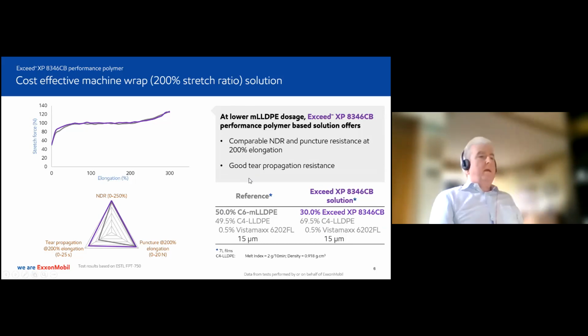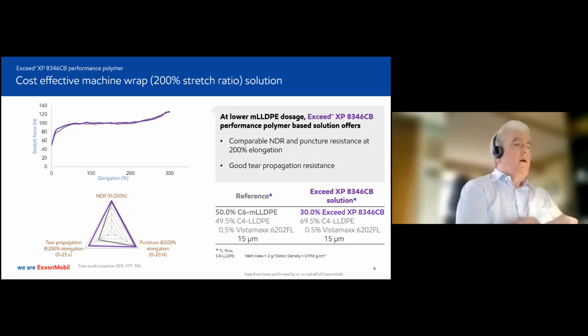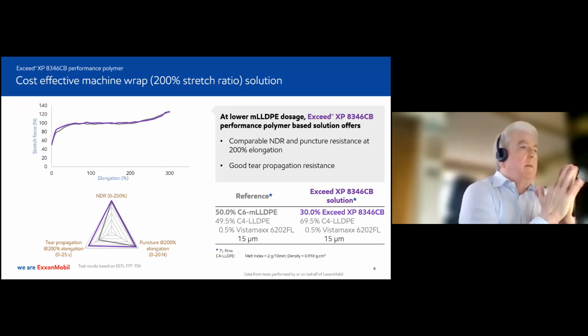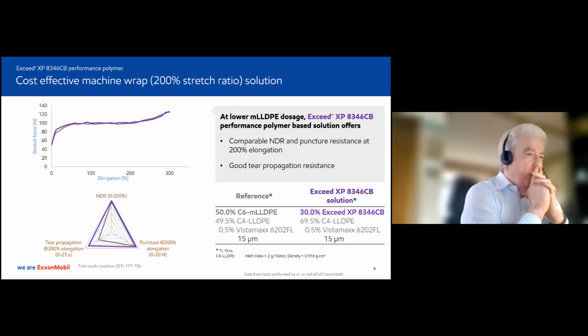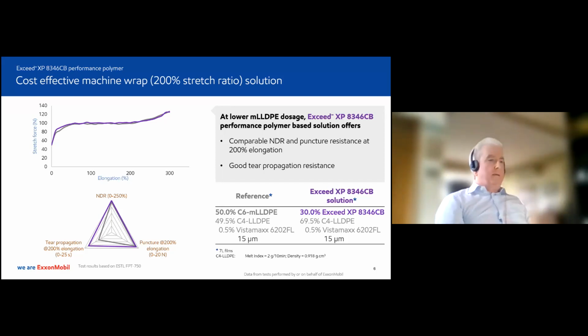The reference material here contains 50% of the conventional metallocene resin, and we're reducing that now to 30% with the Exceed XP8346. So the balance of the formulation is C4-LLDPE, and the Vistamax is our performance propylene elastomer grade that we use as a cling additive. And as you can see, this is designed to be cost effective because of the relatively high level of C4, which many producers want to do. And of course, we've even allowed a higher level of C4.